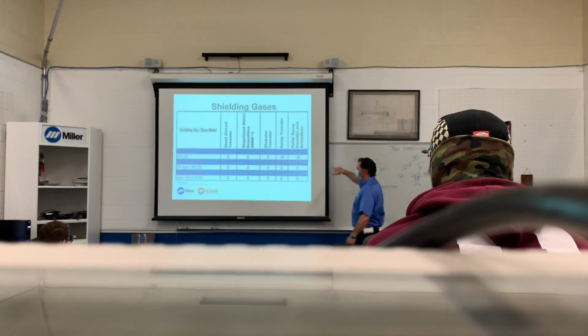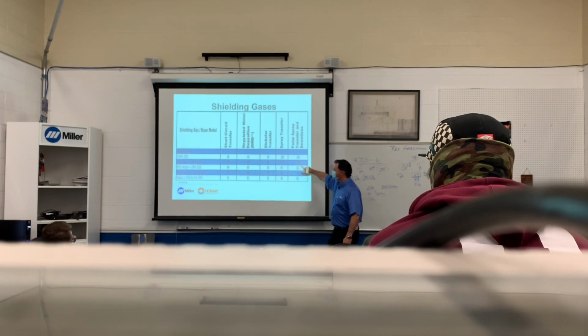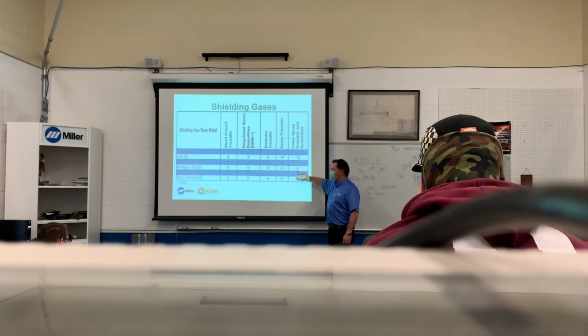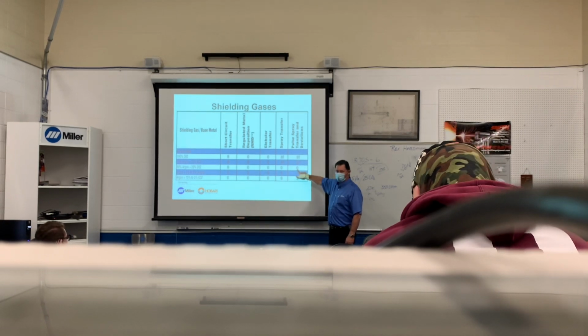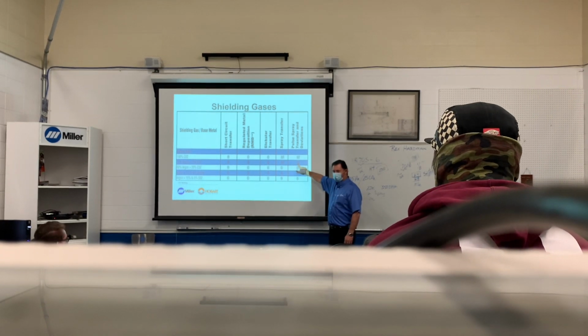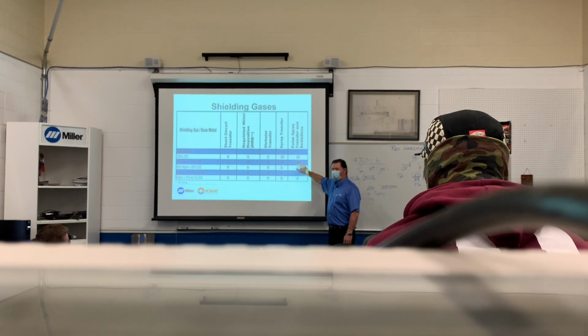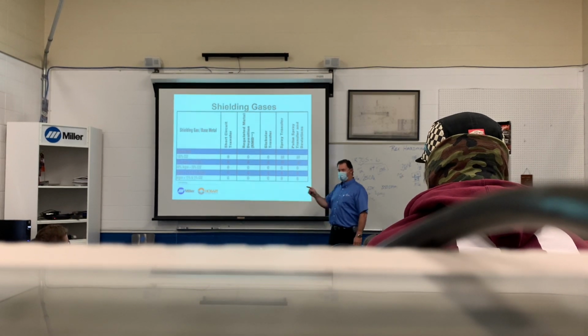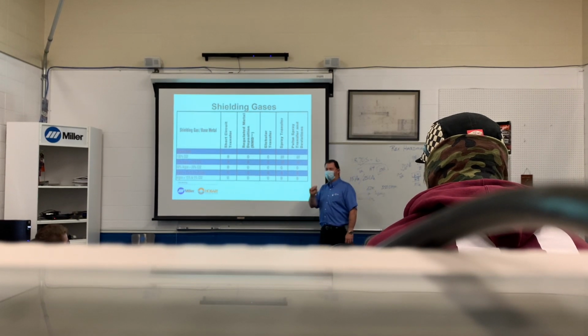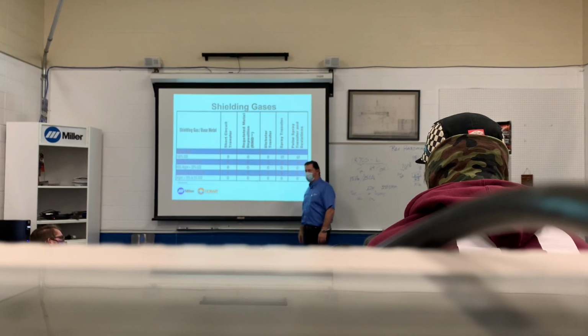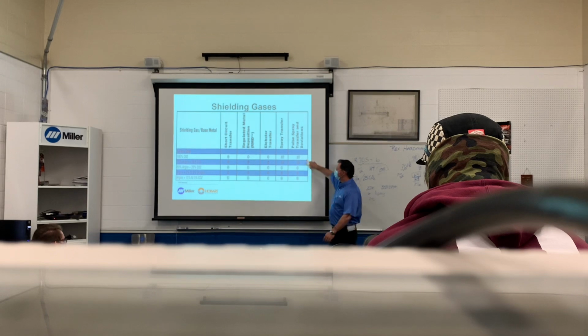So the reason we cannot use it is because, if you look down here, next one down, I need a minimum of 80% argon in order to hit that ionization potential to create a spray arc. Has nothing to do with the pulsing of it, it has to do with the ability to spray that metal across the arc. Okay? So we need that ionization potential of the minimum of 80% argon.